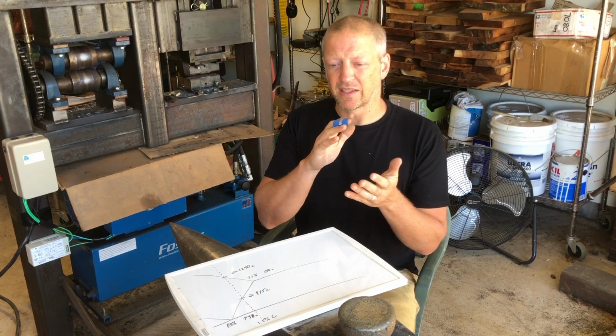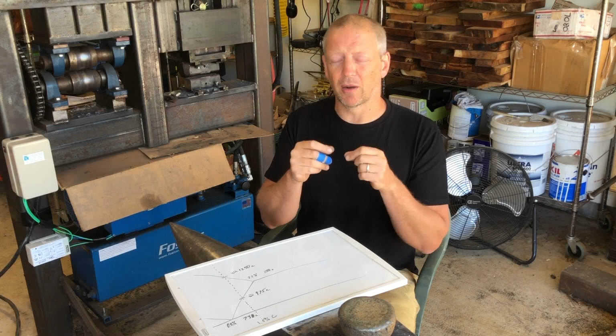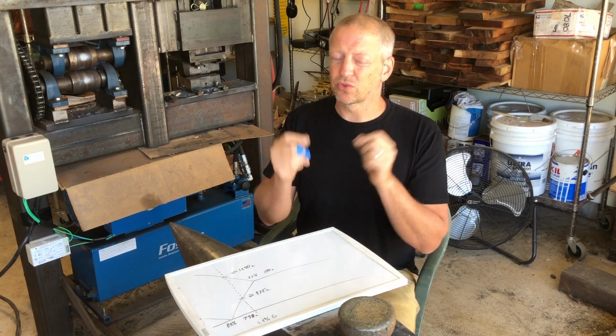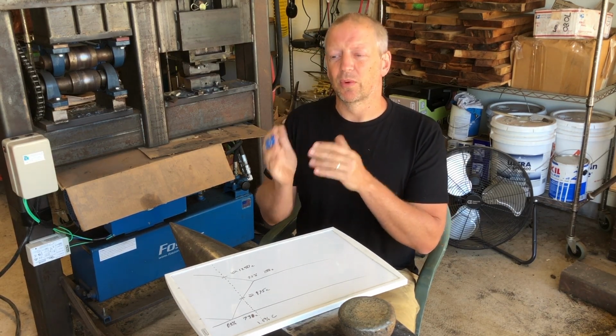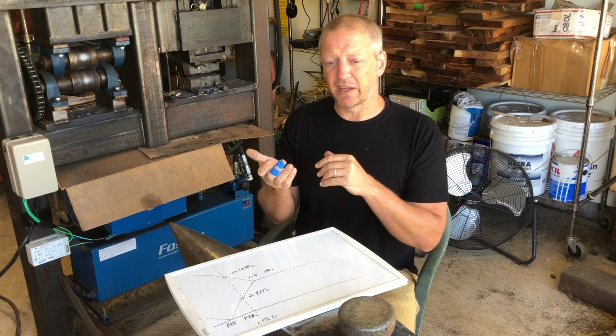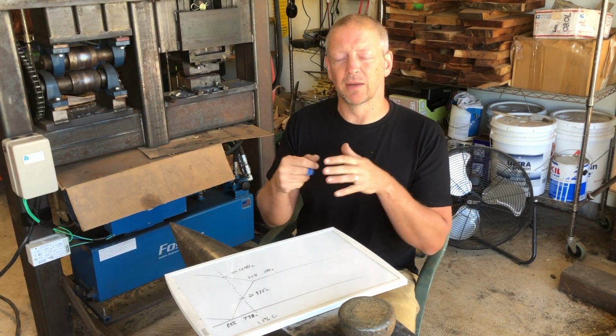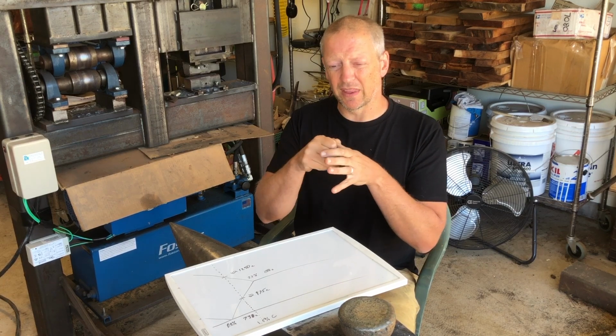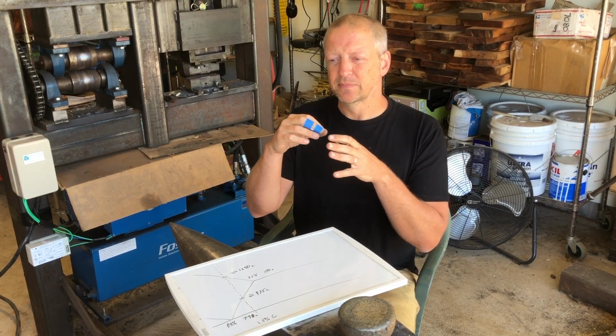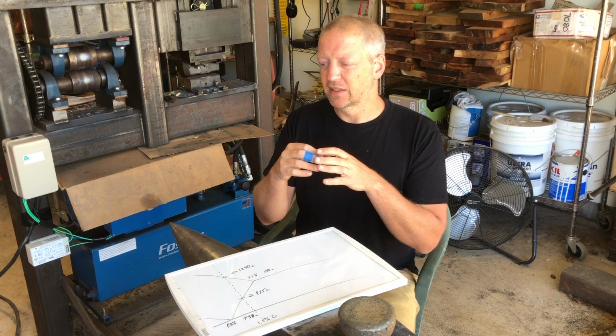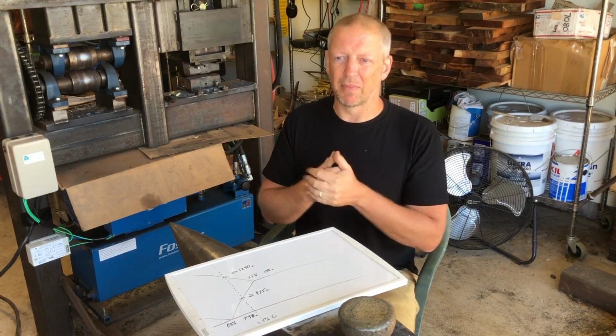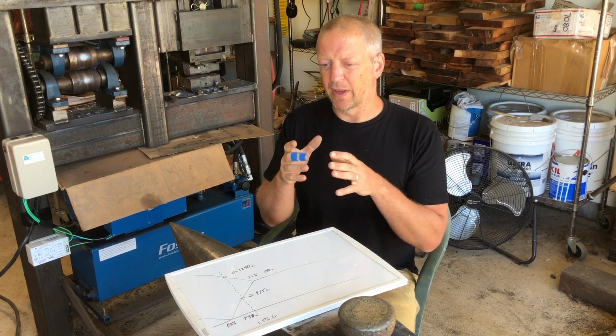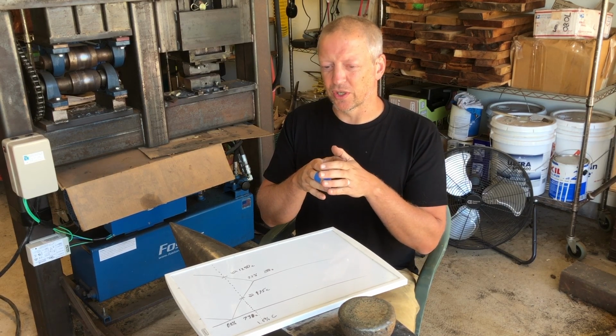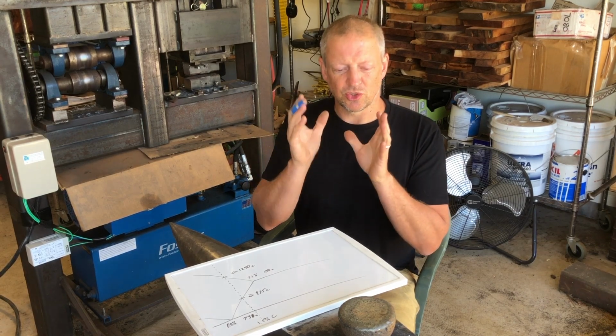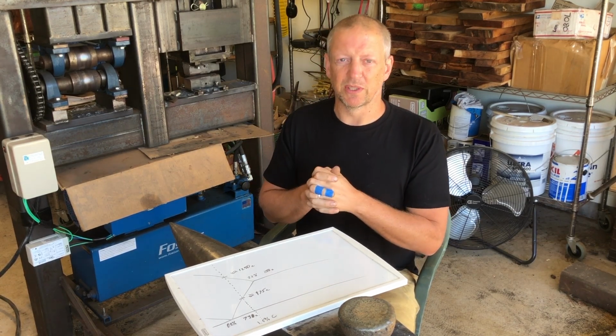The other side of that dendritic structure with very large blocky carbides is that it's going to be incredibly difficult to forge without having fracturing in your steel. Carbides themselves do not forge. They can move within the iron matrix, but they are themselves not at all malleable. So if you have that very dendritic structure and were going to just go straight to forging, it's going to have to be some pretty delicate forging.